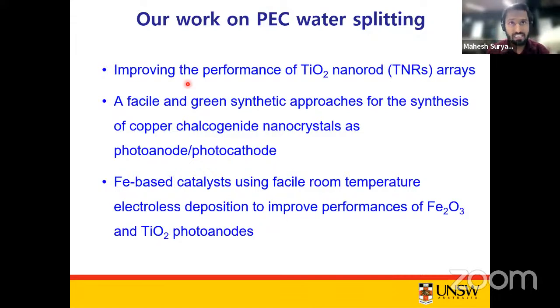So initially, what we have done is focus on the widely explored TiO2 semiconductor photoanode, and then we have tried to improve its performance by simply doping sulfur into the TiO2 lattice, or by simply sensitizing it with narrow band gap semiconductors, which are earth-abundant compounds like copper, zinc, tin, sulfur. Then we have also focused on developing different copper chalcogenide nanocrystals and their thin films using facile and green synthetic approaches, either as a photoanode or a photocathode, or simply for developing an unassisted water splitting system, which I will explain again in my last slides.